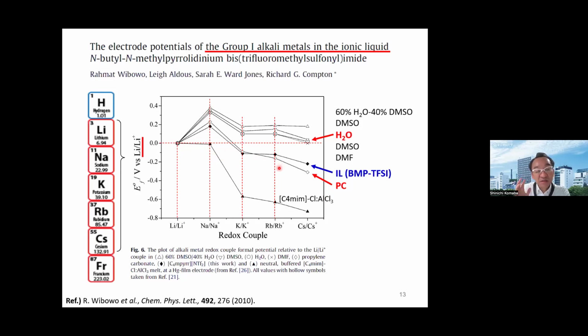But we note that in any electrochemistry or physical chemistry book, E0 values are always referred to aqueous solution, H2O. Then lithium is believed to have the lowest E0 of any element in the periodic table. But actually, in a typical battery electrolyte like propylene carbonate, the E0 is sometimes lower than lithium.